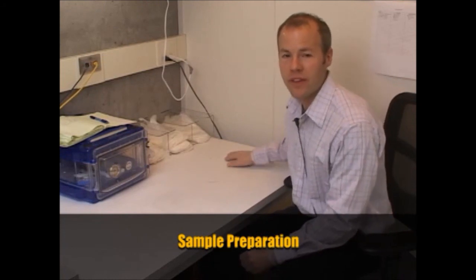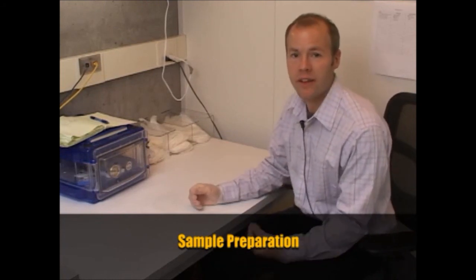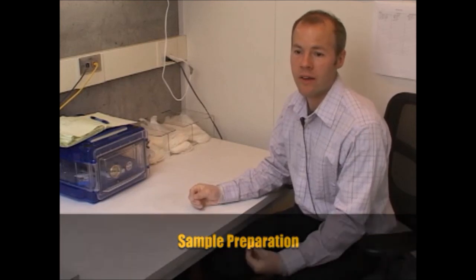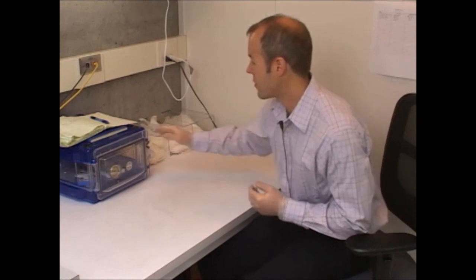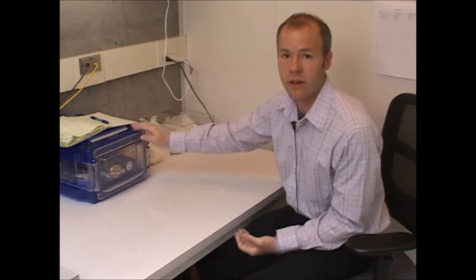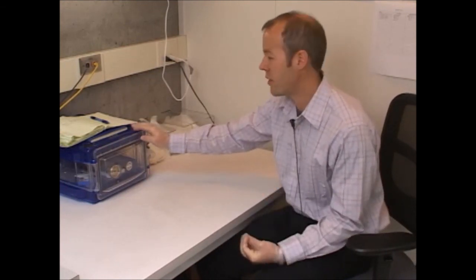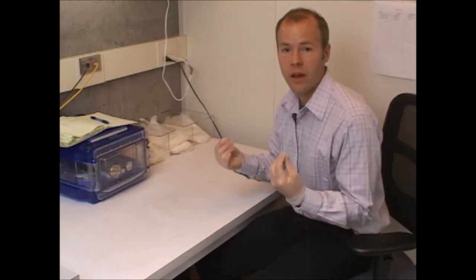Because we're putting a sample into a high vacuum environment, 10 to the minus 5 millibar, a lot of things that exist in the normal environment as liquids or solids can be vaporized. So we want to keep the sample as clean as possible, which includes keeping our finger oils off of it and also any condensation from the air. We store the samples in a desiccator box to avoid a collection of water on those. And then we also glove up with vinyl gloves to make sure that we don't deposit any material on the sample that we're handling.